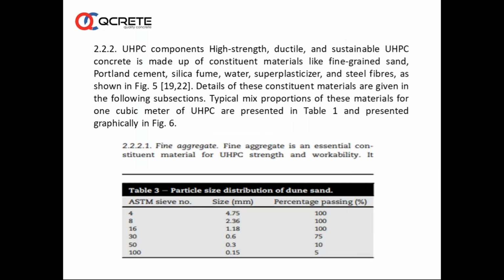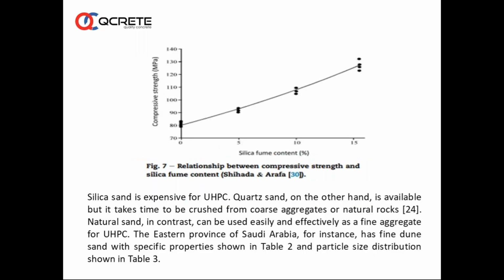So you can see here one of the particle size distribution requirements made by one of the scientists actually, and silica sand is expensive for UHPC. Quartz sand, on the other hand, is available, but it needs to be crushed from coarse aggregates or natural rocks. Natural sand, in contrast, can be used easily and effectively as a fine aggregate for UHPC. And in Saudi Arabia, they have used dune sand, which is easily available.